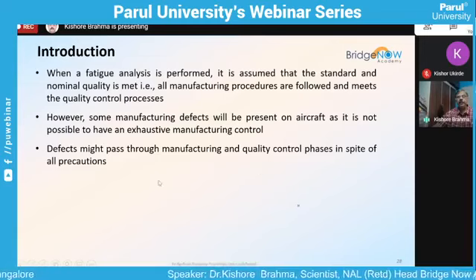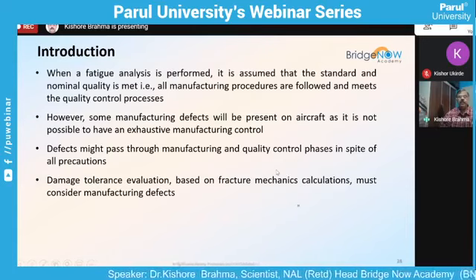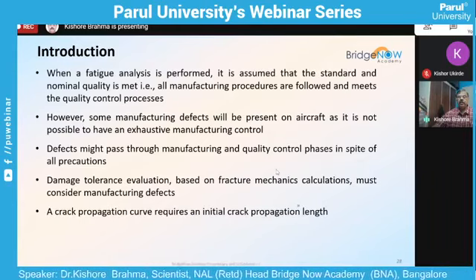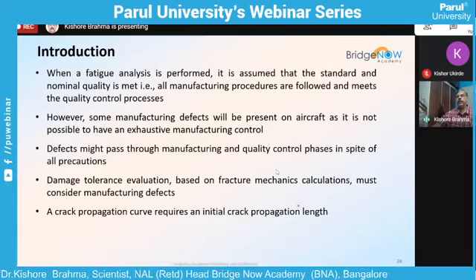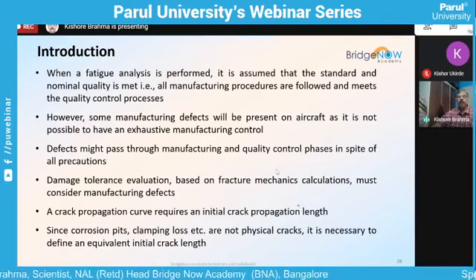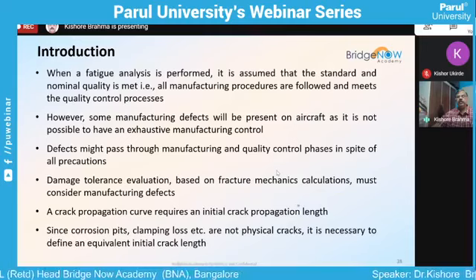A defect might pass through the manufacturing and quality control phases in spite of all precautions. So obviously, during the damage tolerance evaluation based on fracture mechanics calculation, we must consider manufacturing defects. A crack propagation curve requires an initial crack length, because if you are using fracture mechanics, we have to assume an initial crack length. Since corrosion, fretting, clamping, gouges, etc. are not physical cracks, it is necessary to define an equivalent initial crack. So this is the basis on which one has to come out with the equivalent initial flaw size.